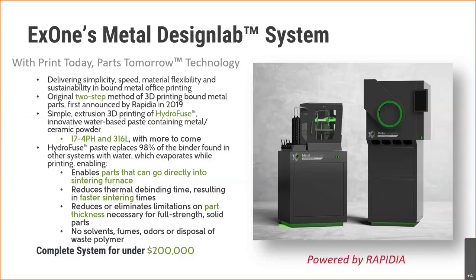One of the other advantages of this system is that, unlike other systems that use this type of printing technology, because we use so little binder, we can have fully thick solid parts. So if you have a part with, let's say, a 30mm or 50mm wall thickness, you can have a fully thick solid part using this technology because we use so little binder during the printing process. And all of this is under $200,000.